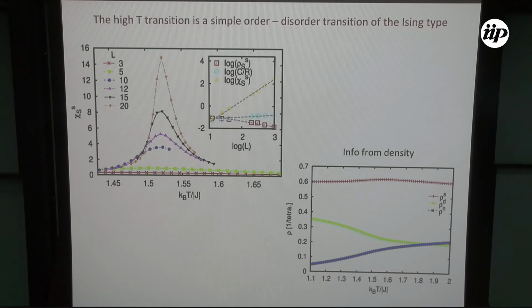Now, that explains the first transition, and the second transition is a simple order-disorder transition. This is just showing the susceptibility and how the susceptibility scales. It's just a normal Ising type transition. What's happening at higher temperatures, you can see from here, this is the density in the system of single charges, double charges, and just the neutral case. Because of thermal excitation, the number of neutral sites you have is comparable with the number of double sites you have, so this mechanism is no longer at work and the system simply disorders completely.